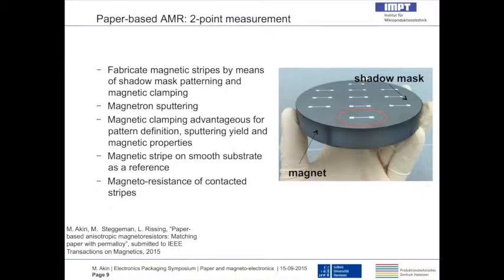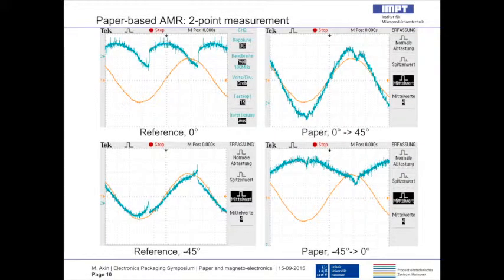And then once we made these samples and contacted them, we measured the magnetoresistance. And what we found out is the following. Looking at the reference sample with the electric current parallel to the magnetic field, we have obtained the following characteristic. The blue curve is the change in voltage, and so it's the change in resistance. And the orange curve is the change in magnetic field. And they both are shifted by a pi/4 phase. So basically you can move that peak of the blue curve to the center of the chart. And so what we see here is basically what I have shown you in the first experiment, that you have an increase in electrical resistance once you have that configuration on a smooth surface.